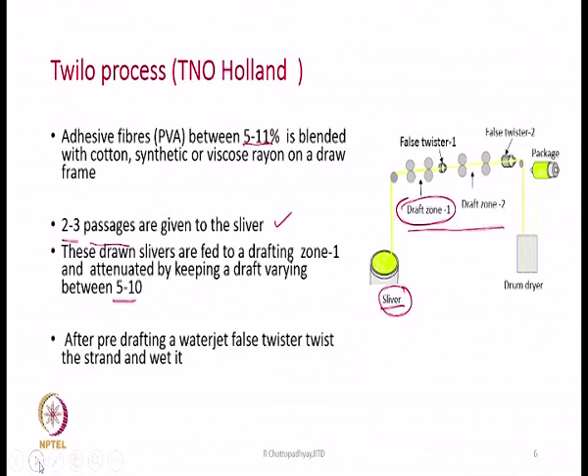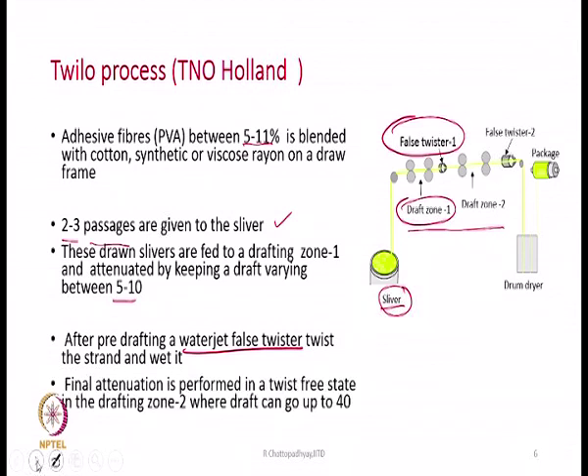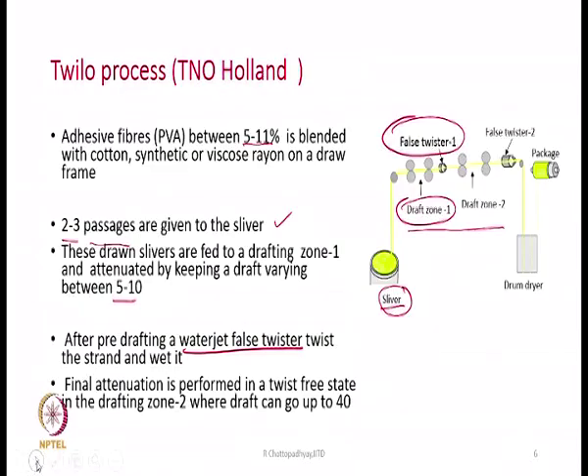Now, after drafting, what do we do? We make the fibers pass through a false twister, which is shown here, and this is a water jet false twister, to twist the strand, because we want to give it a round shape. The very quick way to transform a flat sheet of fibers into a round shape is by the method of twisting. So, we give some twist, and we use a false twister here, because we finally do not need any twist at this stage. So, false twister 1 will be twisting the bundle of fibers which is moving out from the draft zone 1.